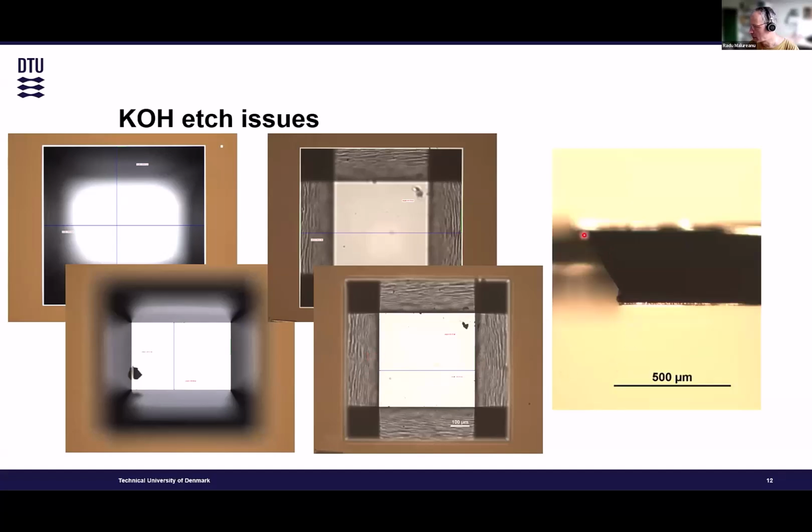So when we did that, we discovered that, this is silicon, this is basically air, rather than having a nice 1-1-1 etch direction, we have some kinks here. We were expecting basically this to be the profile. That makes the membrane bigger, and that's one issue. But also the fact that we have something happening here means that we are not controlling, this is the membrane, some chemistry at this level.